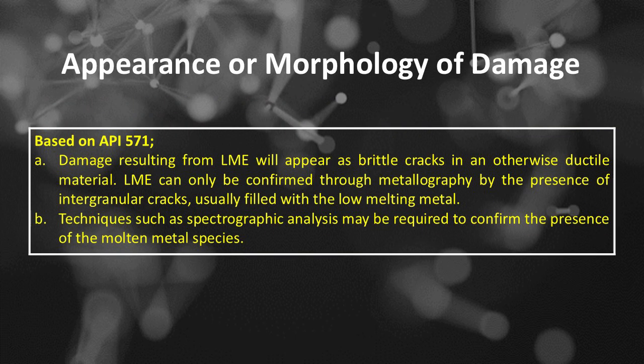Liquid metal embrittlement. Appearance or morphology of damage based on API 571. Number A, damage resulting from LME will appear as brittle cracks in an otherwise ductile material. LME can only be confirmed through metallography by the presence of intergranular cracks, usually filled with the low-melting metal. Number B, techniques such as spectrographic analysis may be required to confirm the presence of the molten metal species.